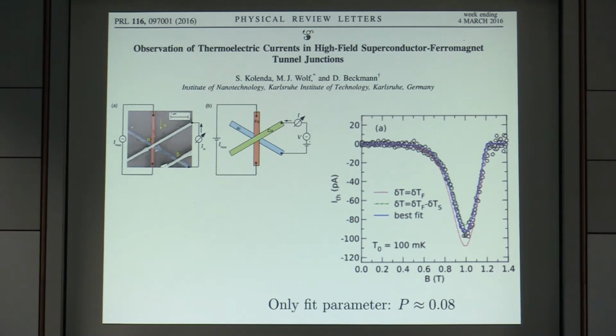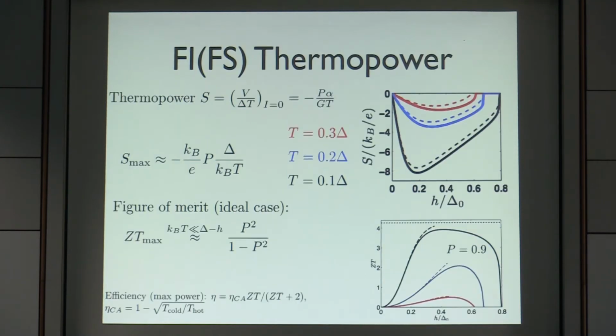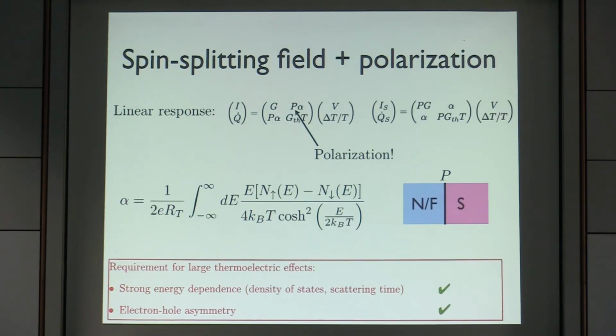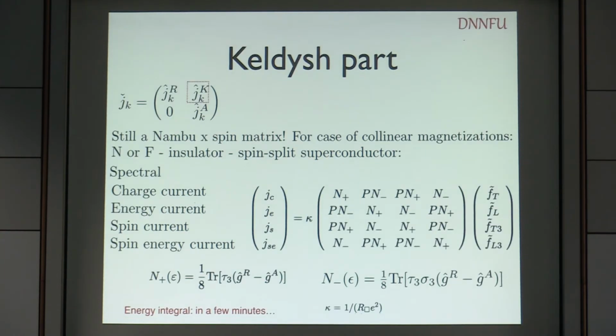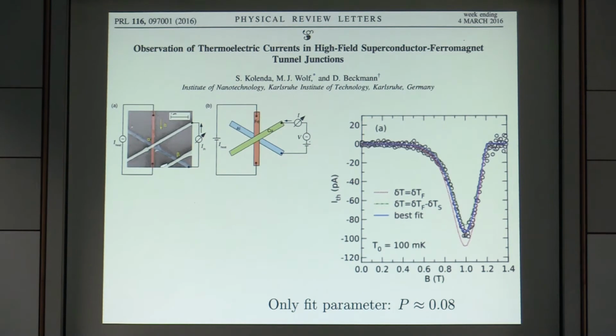Yes. The role of the magnetic field? Okay, good. So I tried to point it out. Let's look at this. The role of the magnetic field is to generate this exchange field in this setup. If you don't have any magnetic field, then there is no exchange field inside the superconductor, and this means that there is no spin-split density of states there either, which means that this difference here is 0. If you apply a magnetic field, then the spin up density of states gets shifted to the right, and the spin down density of states gets shifted to the left, and then you get the difference here. So there the ferromagnet doesn't play a role of the exchange field; it plays the role of a spin polarizer. So indeed, you need these two components. Both of them have to be present. Okay, thanks for the question.